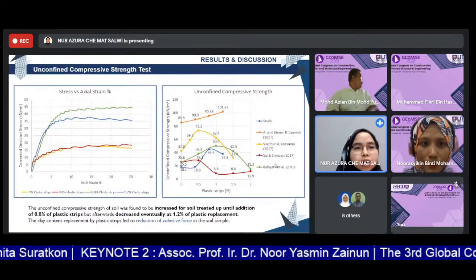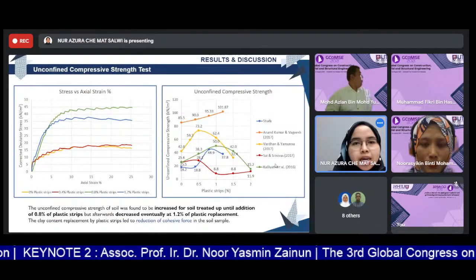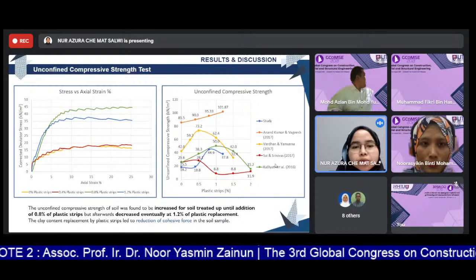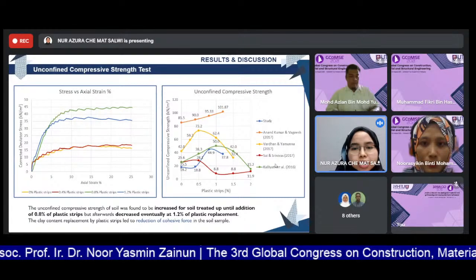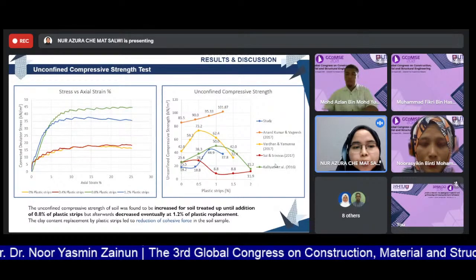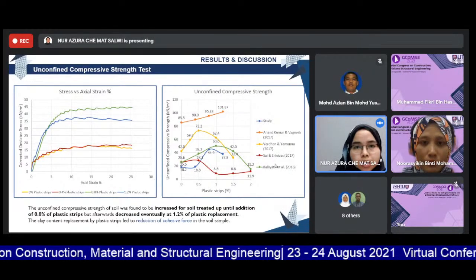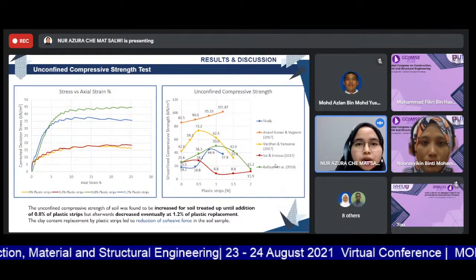For the unconfined compressive strength test, the unconfined compressive strength of soil was found to be increased for soil treated up until addition of 0.8% of plastic strips, but afterwards decreased eventually at 1.2% of plastic replacement. This is because the clay content replacement by plastic strips led to reduction of cohesive force in the soil sample.